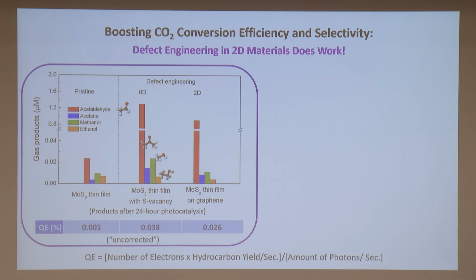And in the thin film case, I give you some quantum efficiency numbers here. This quantum efficiency is calculated from the number of electrons transferred from CO2 to the hydrocarbon. Okay, so you can calculate all the numbers transferred, and then you divide that by the amount of photons you put in. In this case, I should say this is apparent quantum efficiency, because if you have a very thin layer, for instance only a single layer, you actually only absorb 3 to 4% of the light. Most of the light just goes through.